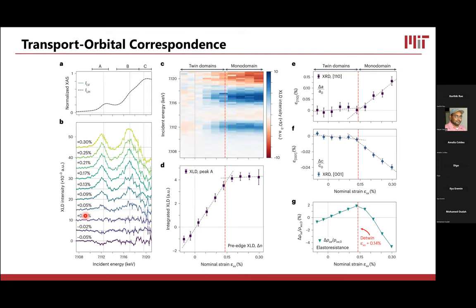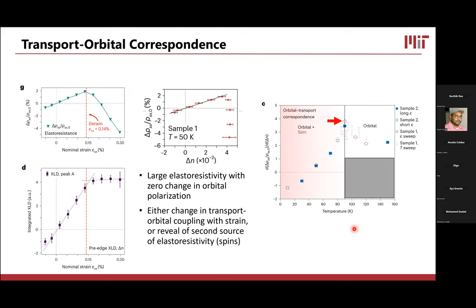There's one more piece of data to look at. I showed you this plot earlier with my XLD and my elastoresistivity. If I now, again, plot my elastoresistivity against my simultaneously collected XLD, I get a plot that looks like this. Within a strain range that corresponds to detwinning the sample, the resistivity anisotropy stays perfectly linear to the XLD. But once I get past the point of full detwinning, the resistivity anisotropy has a huge change with strain, even as the XLD stays completely flat. So even though the orbital polarization isn't changing at all, the resistivity anisotropy is changing quite a bit.